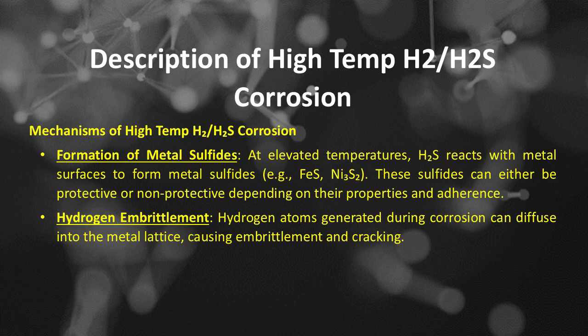Mechanisms of high-temperature hydrogen or H2 and hydrogen sulfide or H₂S corrosion include, the first, formation of metal sulfides. At elevated temperatures, hydrogen sulfide or H₂S reacts with metal surfaces to form metal sulfides, such as iron sulfide and nickel sulfide. These sulfides can either be protective or non-protective depending on their properties and adherence. The second is hydrogen embrittlement. Hydrogen atoms generated during corrosion can diffuse into the metal lattice, causing embrittlement and cracking.